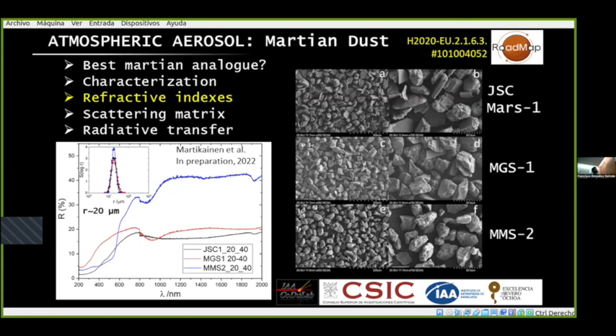In this case, what we use are the large particles, these are the largest particles. These are not representative of Martian dust. Martian dust will be around there and below. But these ones are very nice in the sense that you can measure reflectance spectra. You can compute the scattering characteristics inside the dust using a ray tracing optics method, which is being applied by Julia. And from this, you can retrieve the optical constants, in particular the absorption index.